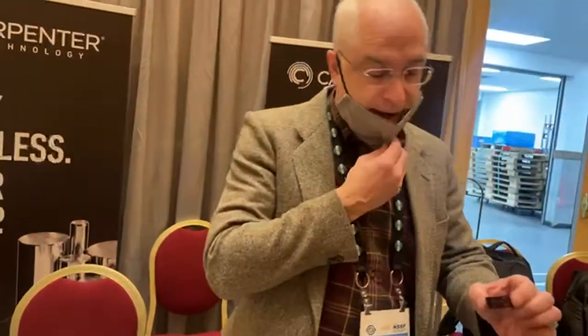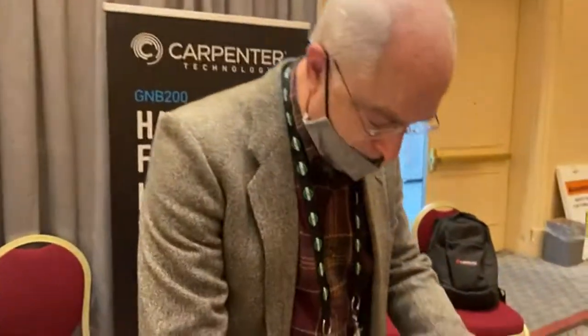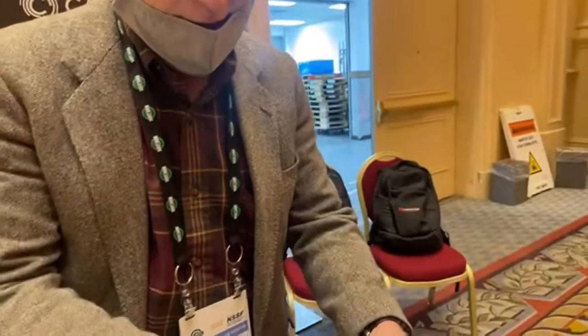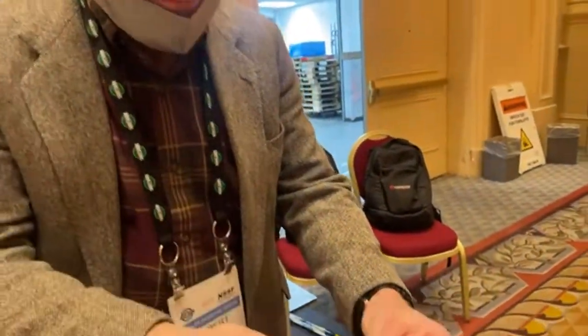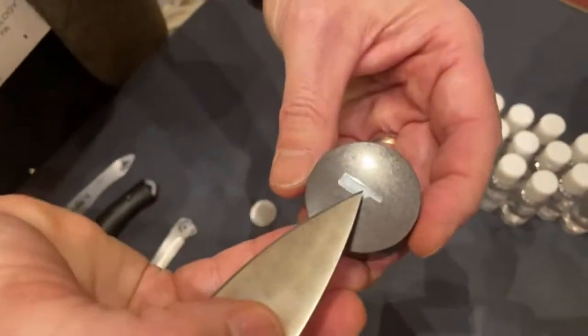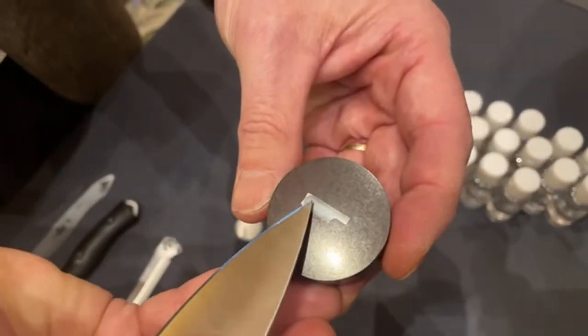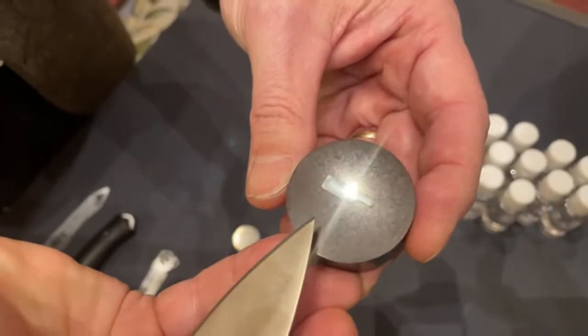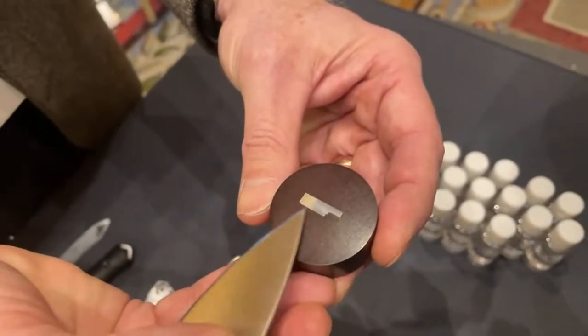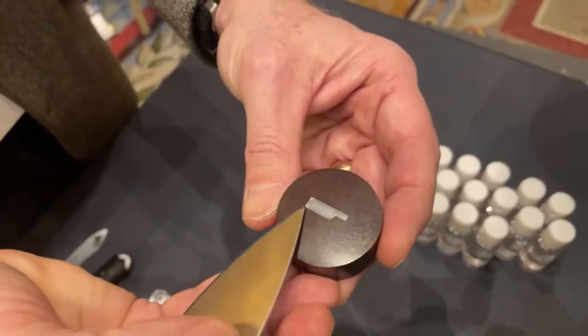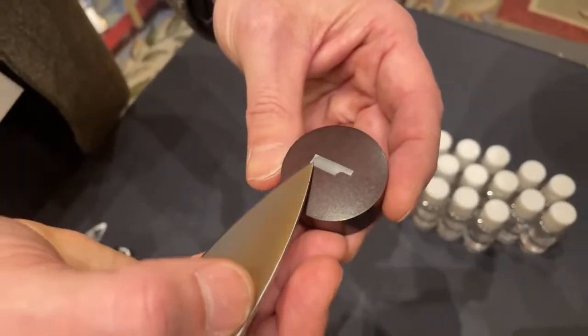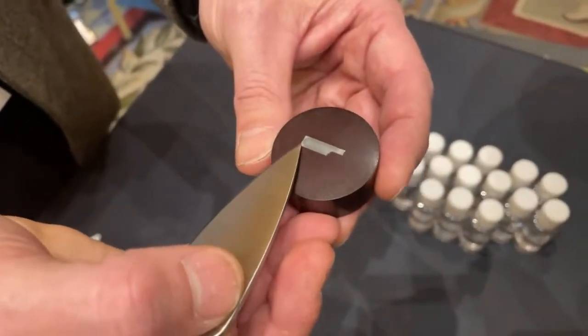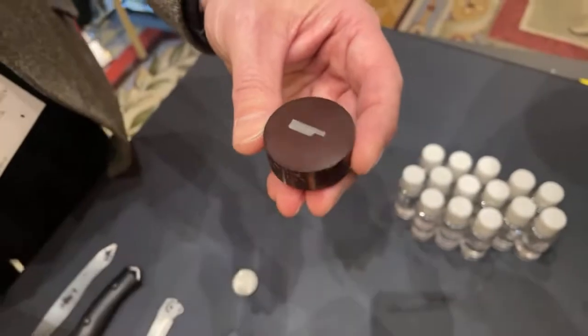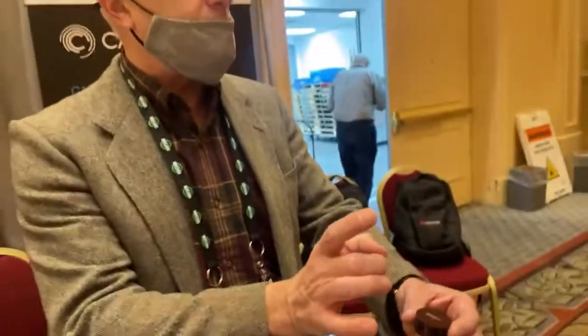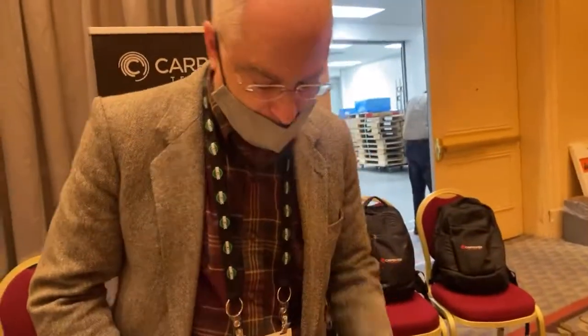Right. But in fact, if you cut it in half, you can actually see where the carbon does not go, which is in the middle, because you're diffusing it in on each face. You can see it etches differently, and you can also see in the corners they look different because we're actually putting too much carbon in the corners because it's coming in from two different directions.